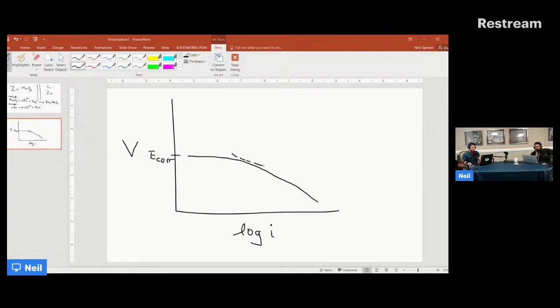And so, okay, great. You have your Tafel slope. The cathodic one's not usually as much of a pain. The anodic one, you'll get something like you described. You might get something like this, and then this, and there might be like two. I'm drawing it kind of badly and maybe exaggerated, but just so you see, there's two slopes. This is the one that you would use to calculate your E corr and I corr, right? Where basically those intersect. But then you might have this other slope right here.